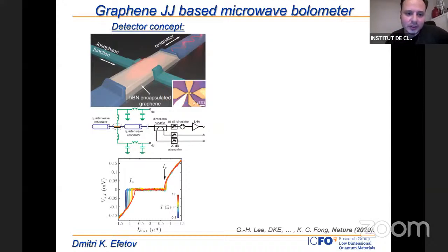Along the lines which I just discussed, low heat capacity and superconductivity for sensing, what we did, led by Casey Fong, before we even knew that graphene can intrinsically be superconducting, was make graphene quasi-superconducting by making Josephson junctions, proximitizing it with niobium nitride or niobium. We already made detectors based on this platform. This is a detector concept which we have. We incorporated the graphene JJ. The JJ goes in this direction, so we can send a supercurrent across the graphene in this direction.